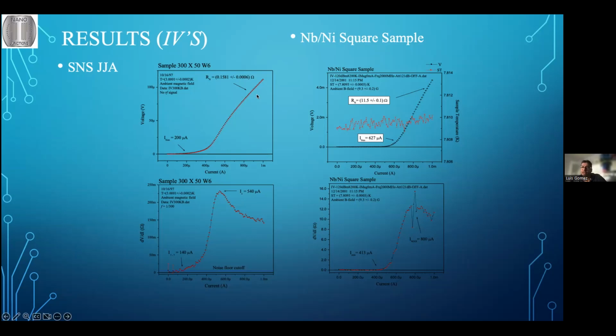So this is the voltage-current characteristic for the first system, the one that has niobium on top of gold. And then this is a similar curve, but for niobium on top of nickel squares, nickel dots. This is a completely different system. The film is actually continuous, so the critical current will be much higher. Here it is determined to be 427 microamps using this criterion, and the current at the maximum change in resistance is about 800 microamps.